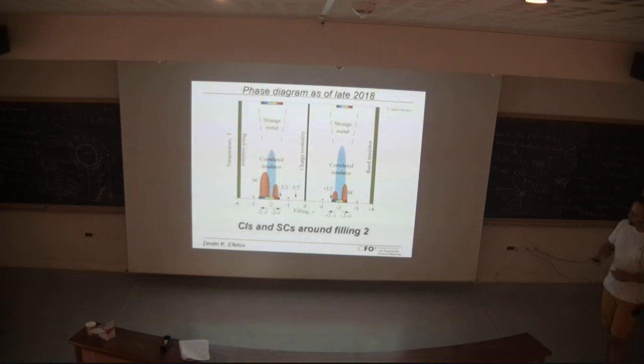And as you can see, this is not my personal data right now, but indeed the correlated gaps vary. The strength of the gap varies from electron to hole side, but also it varies with twist angle. So in principle, this type of diagram is rapidly evolving, and it's not a general picture at this point. Also the superconductors we observed have different TCs, and so far this one here has the highest TC. This is just, I think, empirically what we observe.